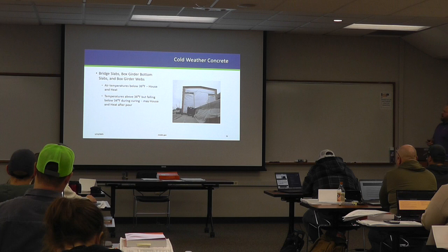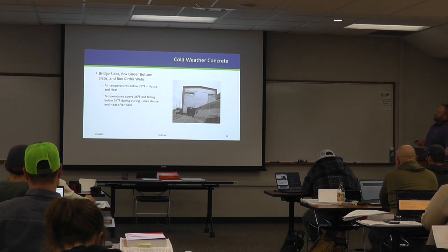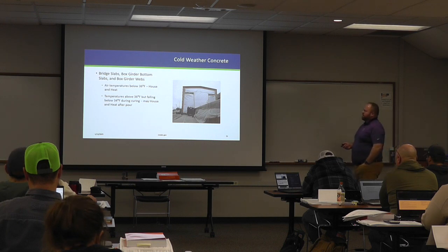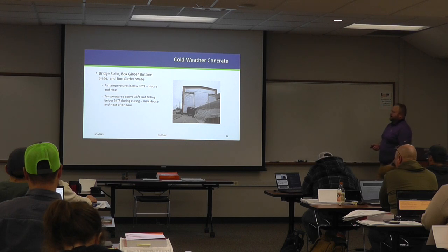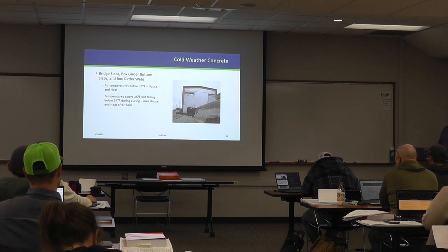If you're looking at bridge slabs, box girder bottom slab, and box girder webs, with air temperatures below 36 degrees, we're going to house and heat. And if there's temperatures above 36 but falling below 34 during the curing, you can house and heat after the pour. I think this is from the 35W bridge when they were casting the box girder segments. They just had a house and heat situation in here.